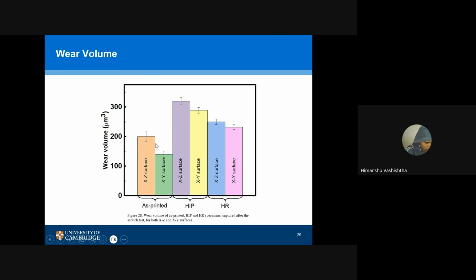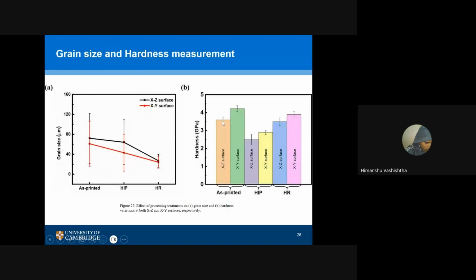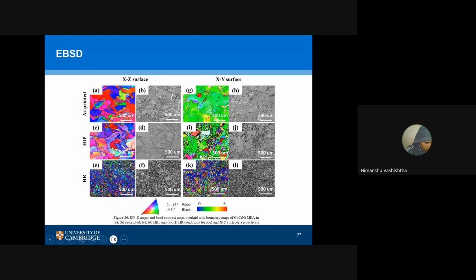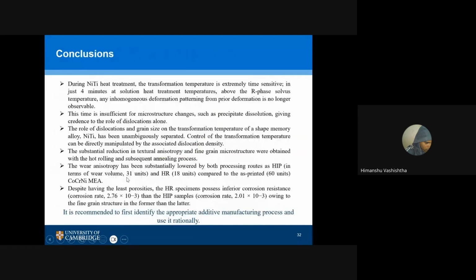Can you see it? It's pretty huge. And that has been almost eliminated in the case of hot rolling. So in that sense, we are saying the anisotropy has been eliminated in terms of wear volume. Similarly, the microstructural anisotropy was also eliminated. Now it's up to you what your application is. So either you can select hot rolling or hot isostatic pressing. These are the corrosion rates. So significant difference is there, but it's up to you where is your application.